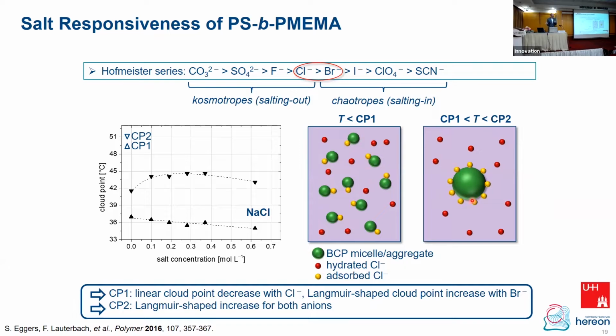So this is like what I said before, like a Langmuir isotherm, because you have the surface of this green ball or this green aggregate, and you cover the surface with this chloride, and that means you have a certain surface occupation density of chloride, and it can eventually be saturated, and that's why you get also this flattening of the curve here on the left-hand side. So there is a certain saturation, and then the surface of the globules is covered completely, and you have no further effect when you add even more of the salt.